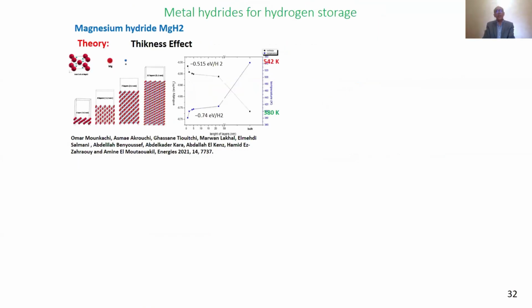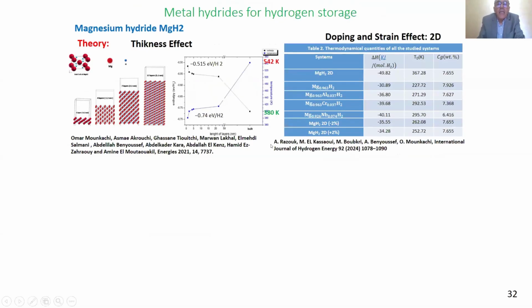Now I go back to the two-dimensional form of this material. This material has a high desorption temperature for the bulk. You see that this is the temperature, more than 500 for the bulk. But by decreasing the thickness of the film to monolayer or few layers, the desorption temperature decreases from 500 to 300. We can also decrease the desorption temperature further by making some substitution in this 2D material. By substituting magnesium with aluminum or chromium or niobium, etc., we can reduce the desorption temperature.